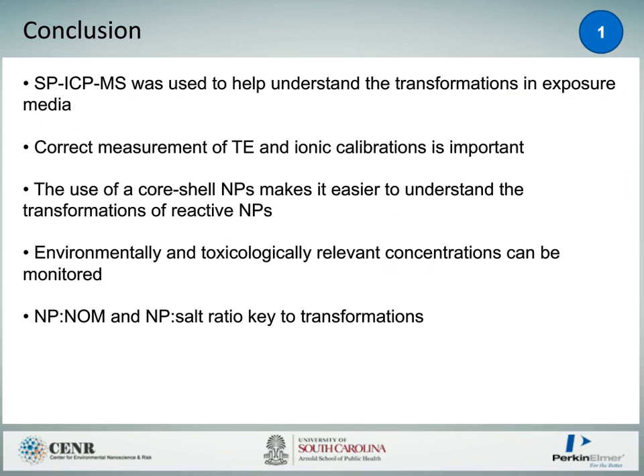So in conclusion, single-particle ICP-MS in this case helps us to understand transformations in exposure media. The correct measurement for transport efficiency and ionic calibrations is incredibly important because you could get false positives very easily. The use of core shell nanomaterials makes it easier to understand these transformations. It would be very difficult to understand if we were just looking at the silver particles alone. And the environmentally and toxicologically relevant conditions can be monitored, so we can go down to very low particle number concentrations. We also showed in this study that nanoparticle to natural organic matter and nanoparticle to salt ratios were very key.